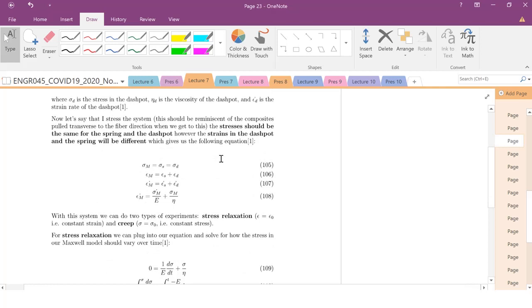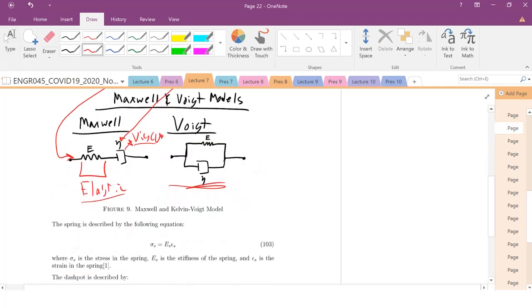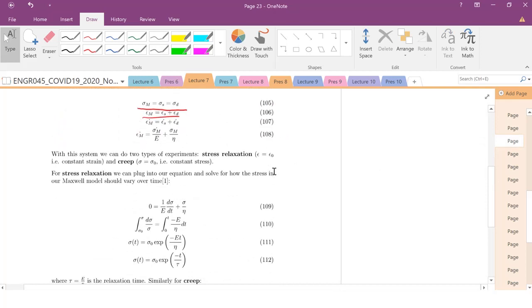When elements are in series, the stress in the whole unit is the same but the strains differ. When in parallel, the strains are equal. If the components are physically attached side by side, they share the same strain; if in series, they share the same stress — the dashpot and spring stresses are equal in series, and strains equal in parallel. You can create complex models to describe the mechanical response of materials.